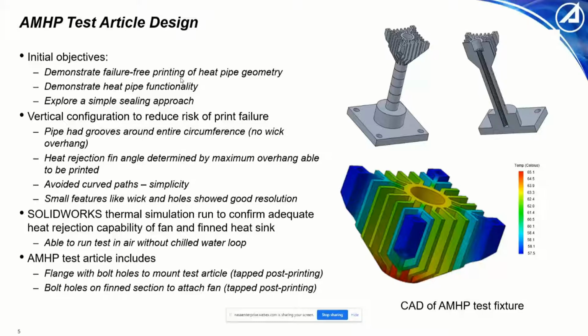You can see we have a fin section at the top for heat rejection on the condenser, and the angle of those fins was determined by the maximum overhang able to be printed, which was 35 degrees. We avoided any curved paths for simplicity in this first design. Surprisingly, small features like the inside of the wick and the holes at the top of the heat rejection section showed very good resolution, so we were happy with that.